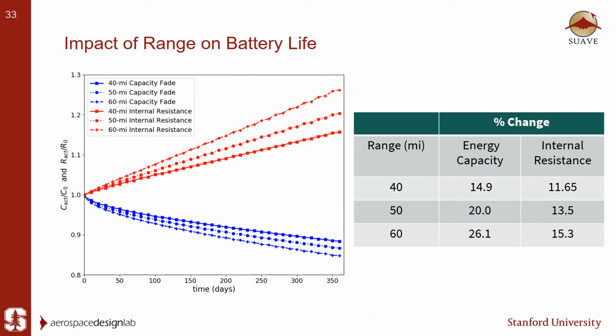Secondly, with regards to range, which we would expect, longer ranges will essentially cause the battery to degrade more. However, what is interesting to note here is that we see about a 5% decrease in the capacity per 10 miles, as well as a 2% increase in internal resistance. Now alone, these parameters are not significant. However, when used in conjunction with the energy consumption profile of the aircraft, response surfaces can subsequently be created to predict the exact time at which a repeated mission can no longer be executed, given the requirements of, let's say, a percentage SOC cutoff, as well as a nominal 10% range reserved flight segment. And this is where the power of this model comes into play.